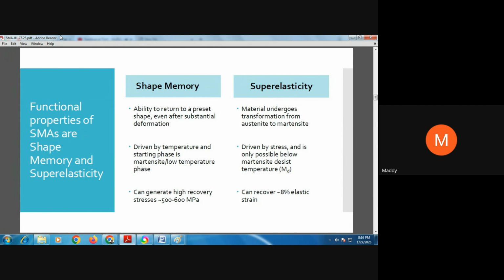On the other hand, superelasticity is induced by stress, and the transformation proceeds always from austenite to martensite. The starting phase has to be the high temperature phase here. Only then can you experience superelasticity. We'll see that down the slides here. There is a specific temperature called the martensite desist temperature, above which you will not see any superelastic effect. The material will behave like your conventional material, with just elastic stress-strain and then plastic deformation. Now, superelasticity, as the name implies, can recover as much as 8% elastic strain.